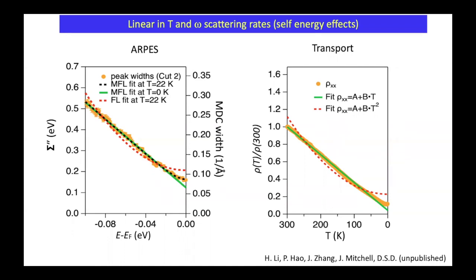Now, this is versus frequency, this is versus temperature. It's not really arbitrary because I know how to connect them with this beta term, of roughly pi. A T squared on this scale is roughly omega squared on this scale. So roughly the same. And again, I just compare the quadratic and the linear, and you can see the scattering rates are quite similar between them.